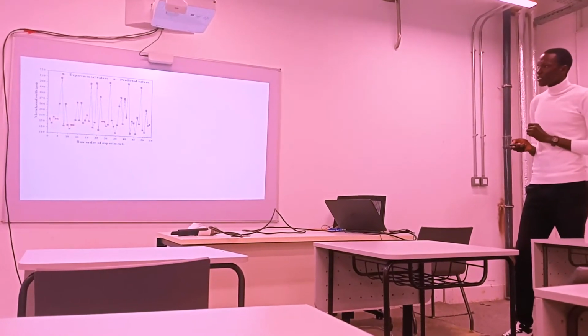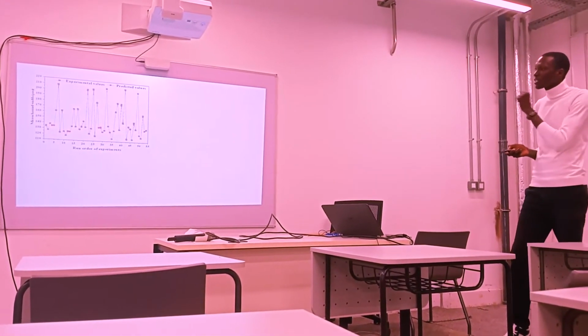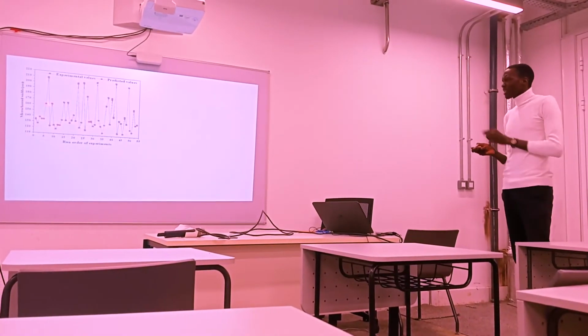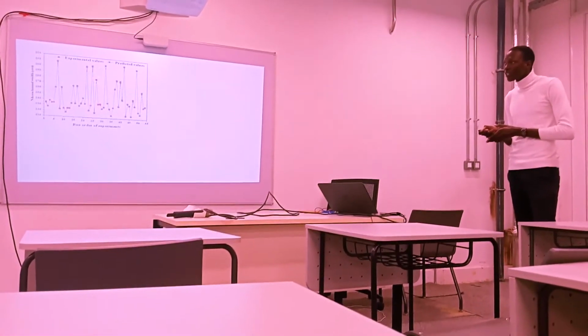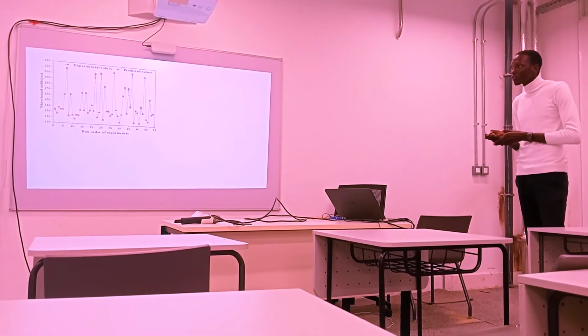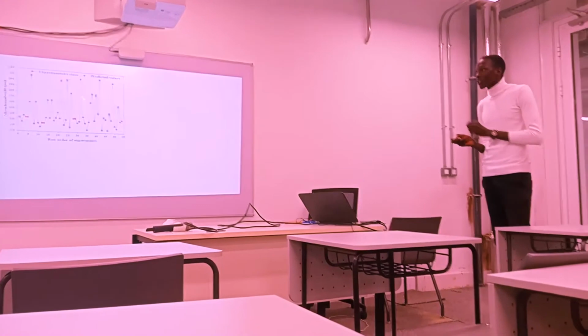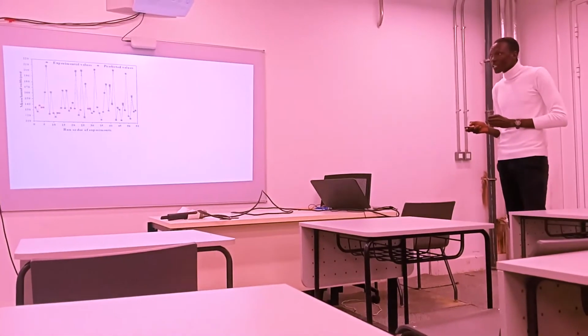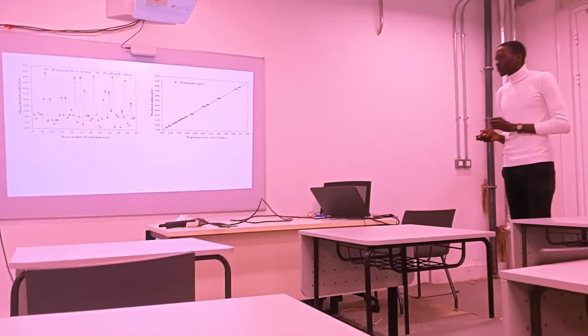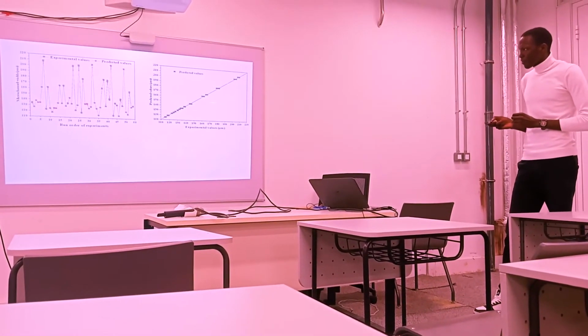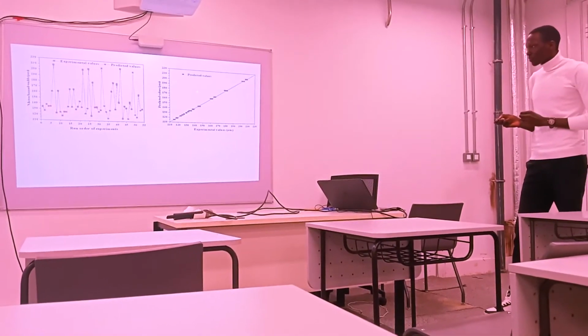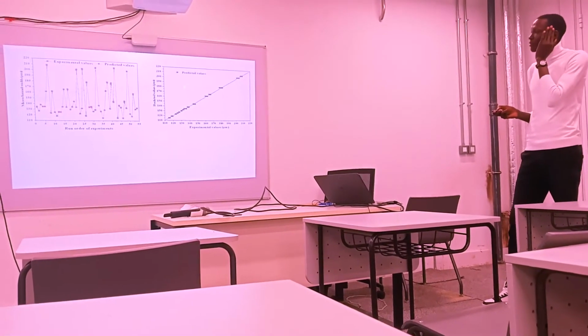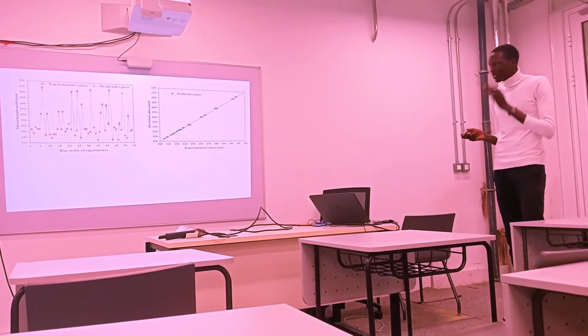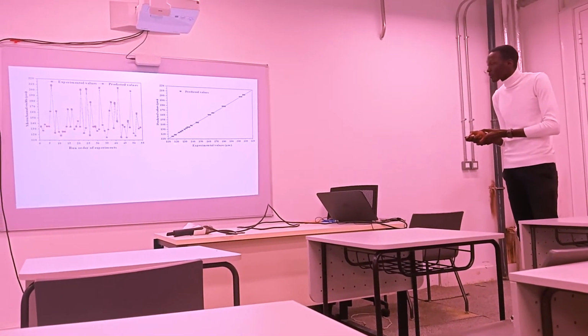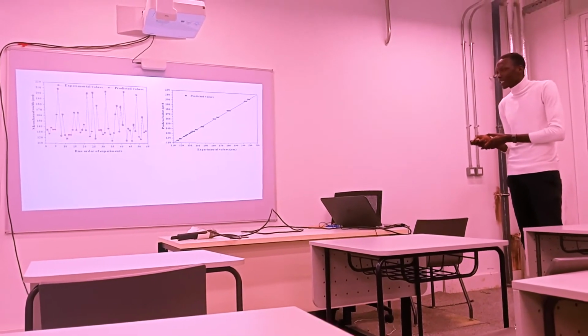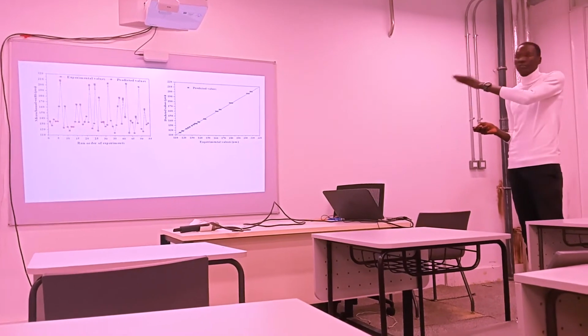Now, we compared the experimental values with the predicted values. Again, we got similar results like we got for response surface methodology. As we can see, the black line again represents the experimental values, and the red lines represent the predicted values. They are very close, as we can see. Then, we plotted this graph to show how close the experimental results were to the predicted values. These are the predicted values, and these are the experimental values. We were able to get the line of best fit, cutting across all the values.